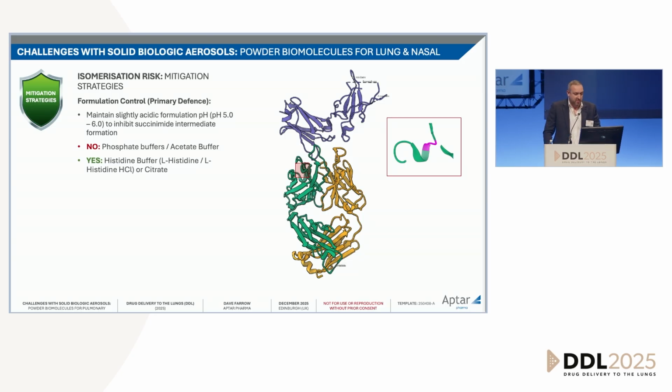No to phosphate buffers and acetate buffers, because of the huge swings potentially in the pH during the drying process. And obviously, once it's reconstituted in the airway surface layer, those microenvironments are going to cause some quite significant degradation issues. And yes, to histidine buffers and citrate buffers. And so if our modality already comes in one of these phosphate-based buffers, we're already starting to think about, look, let's get onto a dialysis, let's get onto a buffer exchange nice and quickly.